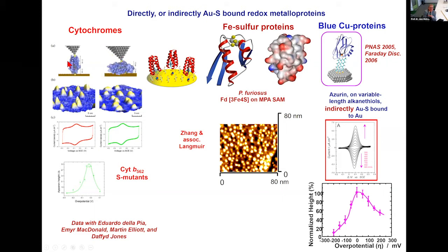And then the molecule can actually bind directly to gold electrodes, either directly to a single electrode surface where we have nice voltammograms. That is already unusual, when you can bind a protein directly to a surface and get good voltammetry out of it. Or it can be hooked up between two gold electrodes and give very nice pictures, images, and very nice tunneling spectroscopy.